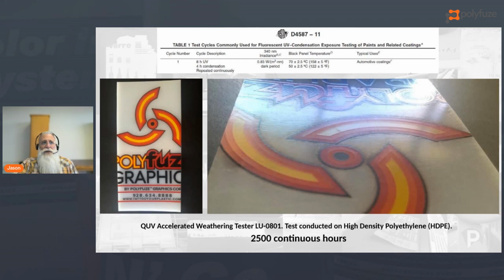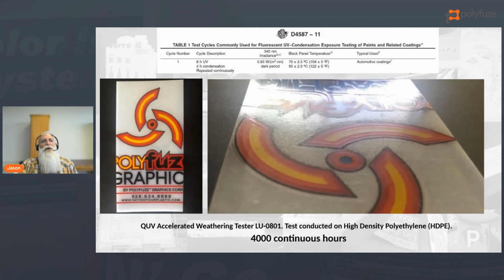This is accelerated weatherometer testing. In this particular illustration, it is QUV testing specifically, 8 hours of UV followed by 4 hours of condensation. The irradiance factor of the bulbs that are used are up there at the top. Typical time frame is about 2,000 hours for most tests. This is what it looked like at 2,500 continuous hours. Getting into the 4,000 hour range, again, no degradation whatsoever.